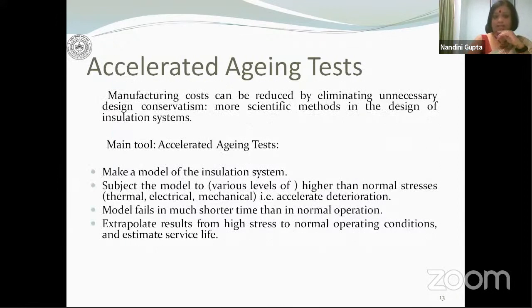So you may be in a situation to be able to say that if a material breaks down in 2 hours at X kV per centimeter, but in normal operating conditions I only expect 1/10 of X kV per centimeter, so under X/10 kV per centimeter it will take me 10 years to break down. I'm just giving you some rough estimate, but it is not as straightforward or as linear as I'm making it out to be. And this I will discuss later.